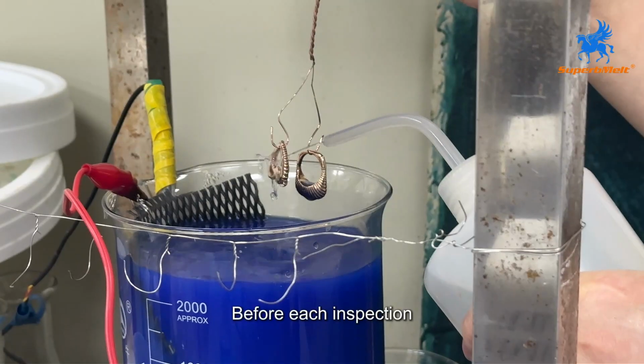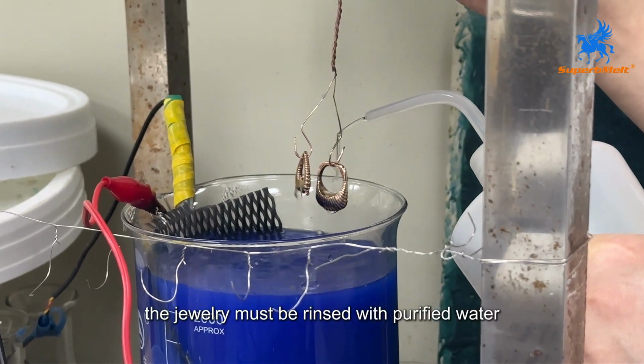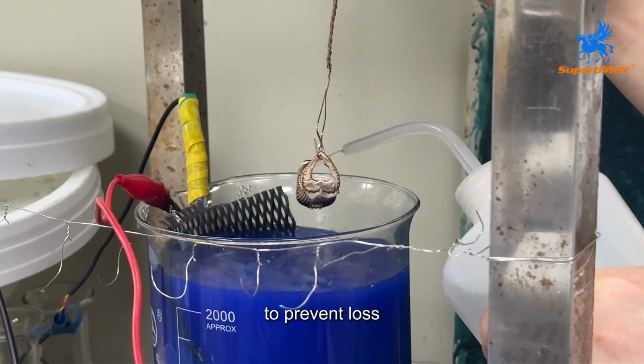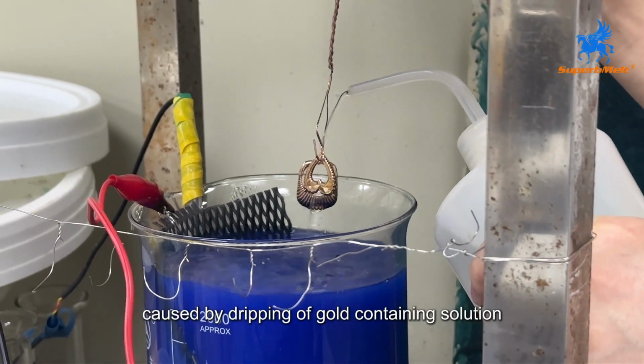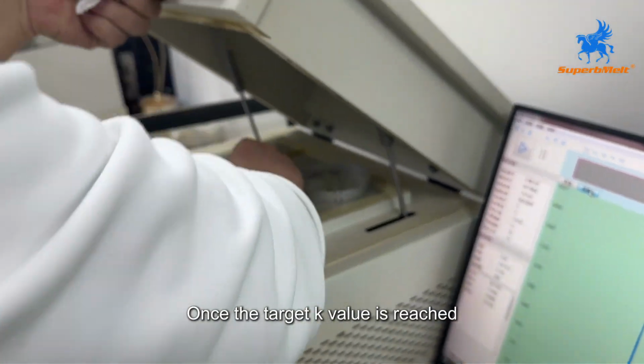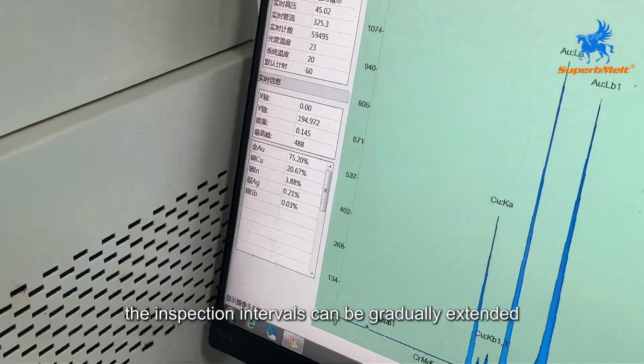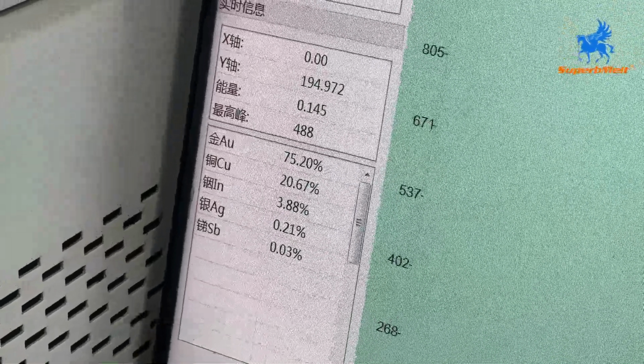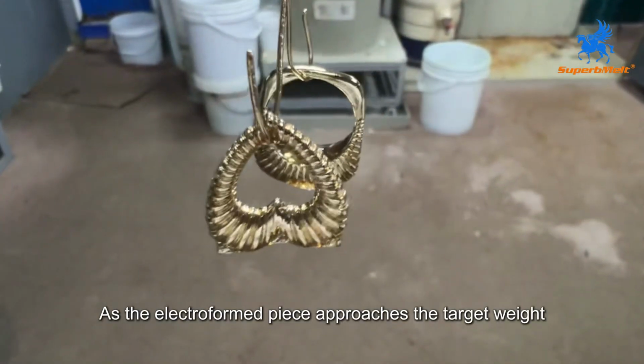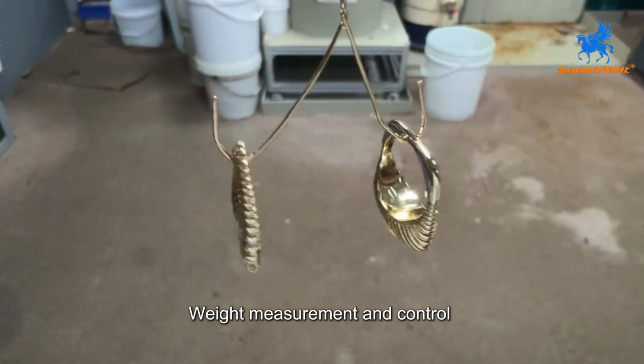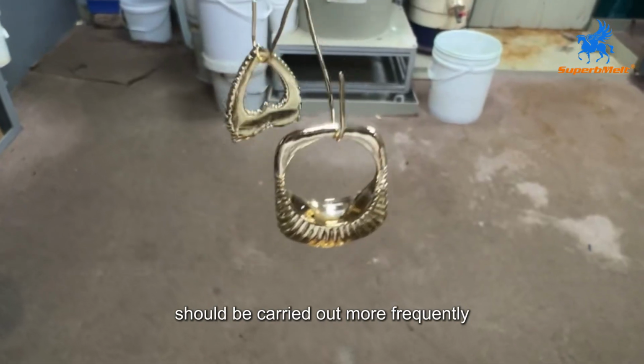damaged. Before each inspection, the jewelry must be rinsed with purified water to prevent loss caused by dripping of gold-containing solution. Once the target K value is reached, the inspection intervals can be gradually extended. As the electroformed piece approaches the target weight, measurement and control should be carried out more frequently.